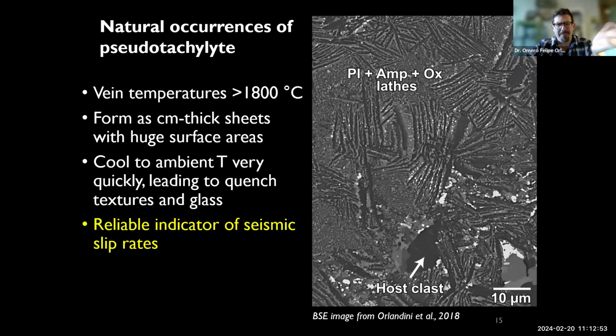temperatures of these things in experiments are super, super duper high, but they form these very thin sheets with huge surface areas against rock that is not 1800 degrees Celsius. And so they tend to quench really, really quickly. And you get these beautiful quenched textures in all of the microlites that make them up.